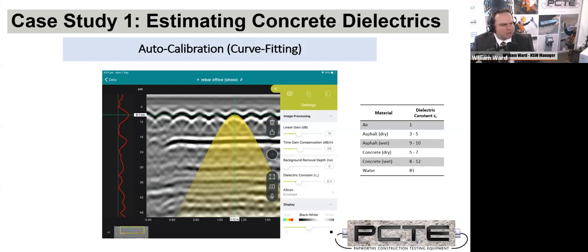The basic one there is you do need to be consistent. Stu is here using the energy peak from the A scan to pick his depths, and he's calibrating that depth and then reading the other depths from that lower down. It's sometimes more appropriate to take the first strong top band, but it's most important to be consistent.